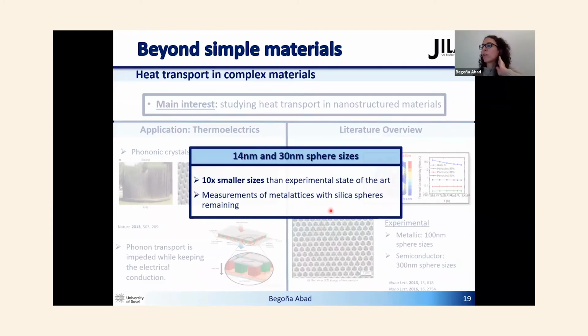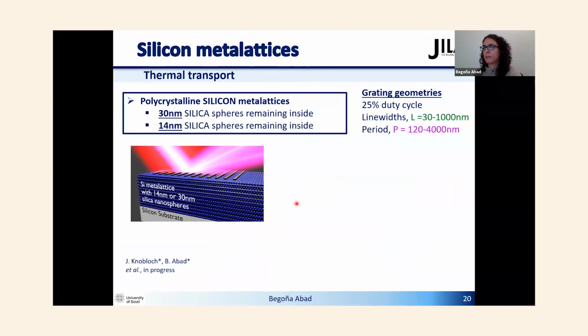So in this work, we are somewhere in between, because we have metalattices with a sphere size on the order of 14 and 30 nanometers diameter. So this is 10 times smaller than the experimental state of the art. In this case, we measure the metalattices with the spheres still inside the metalattice. Okay, so now I'm going to show some of the results that we got.